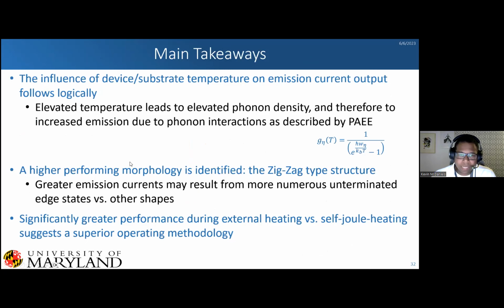And so really the main takeaways here is that elevated temperatures lead to elevated phonon density, and that allows for us to have emission out because we have more phonons to kick out these electrons. We get higher performance out of a morphology that is zigzag shape, which is possibly due to having more numerous unterminated edges versus the other shapes. And then this external heating versus the self-Joule heating that we're currently exploring now.